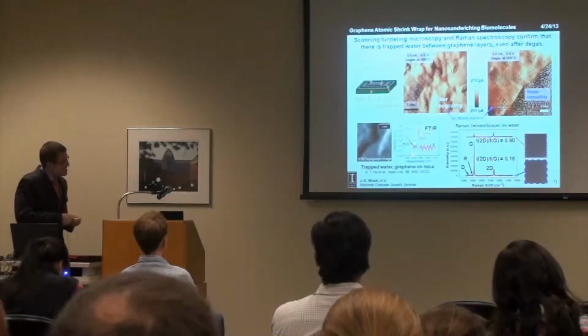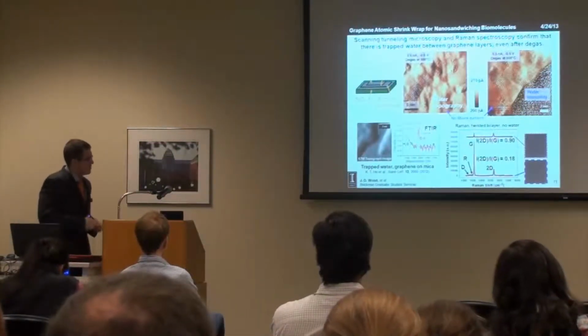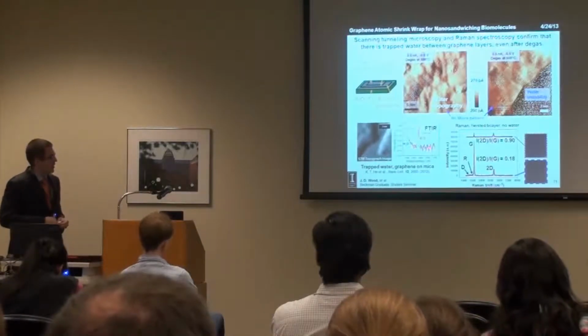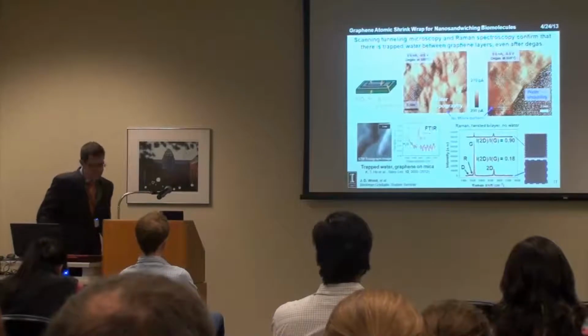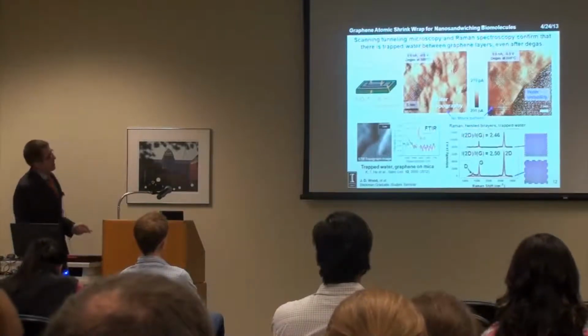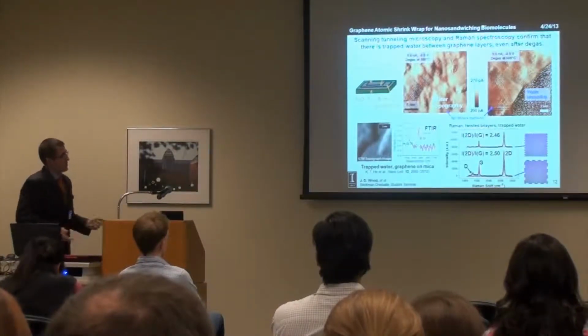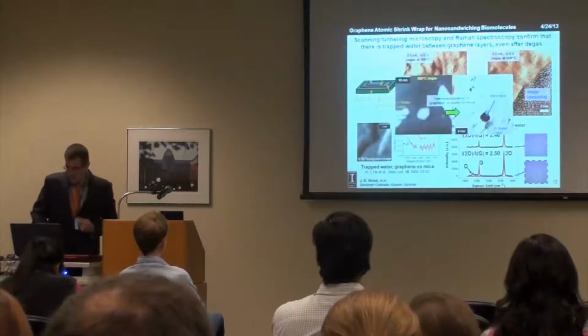We confirmed that it is indeed water from Fourier transform infrared spectroscopy. We can see here with isotopically labeled water that we've trapped water. And we've used Raman spectroscopy to confirm that there's no electronic interaction, that the two layers are decoupled. So the water is stuck there.